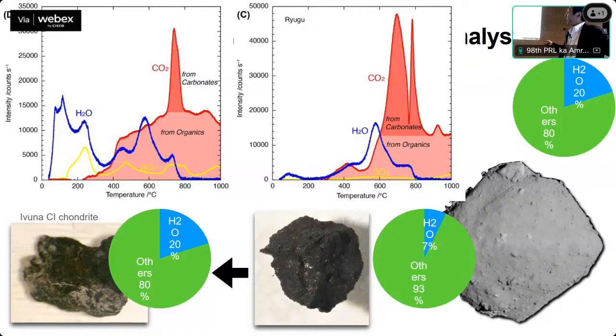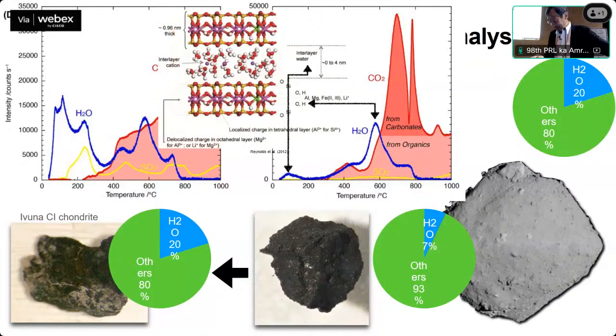This blue curve is the step heating curve of H2O released from the Ryugu sample. At 600 degrees, most of the H2O is released from the Ryugu sample. Why? This is because the H2O is included in clay minerals. Clay minerals have two H2O sites. One is in the structure, and another is between layer and layer. The structural water is placed here, and the interlayer water is placed here, and its evaporation temperature is 100 degrees.